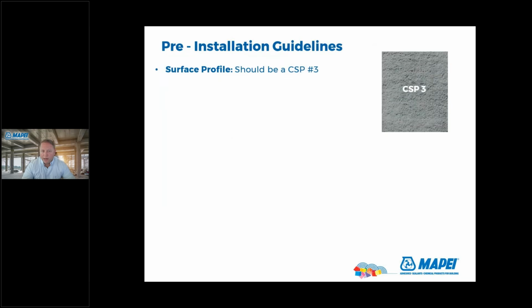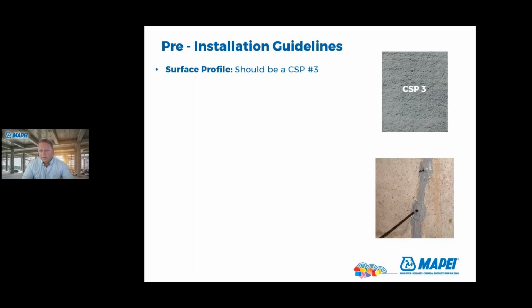So some pre-installation guidelines. One, you want to make sure that you have a surface profile of a CSP of 3. That ensures that the weak cement paste is going to be removed, opening up the pore structure to help with the bonding of the system. You're also going to want to make sure you inject any cracks. Any cracks larger than 10 mils must be injected. What we don't want is the FRP to have any movement and cause any micro buckling in the fibers because those cracks weren't injected.